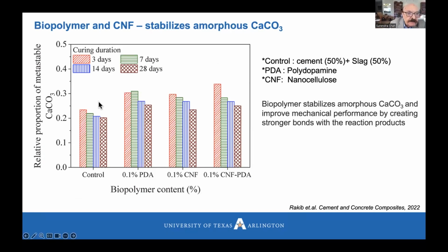So what's plotted here is the relative proportion of the so-called unstable or amorphous calcium carbonate for control specimen, which was half cement and 50% slag. So for control specimen, you get 20% of calcium carbonate after carbonation is amorphous. However, if you add 0.1% of polydopamine, a biopolymer, then you can increase that amount.